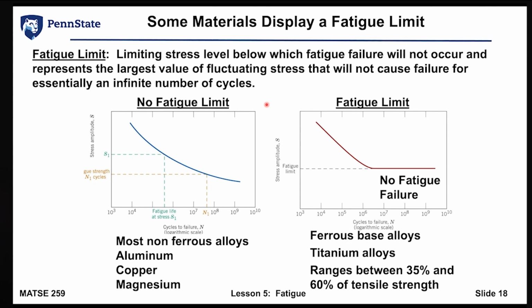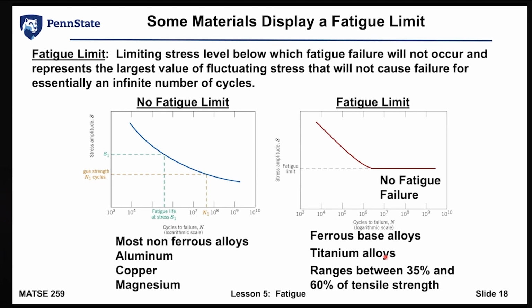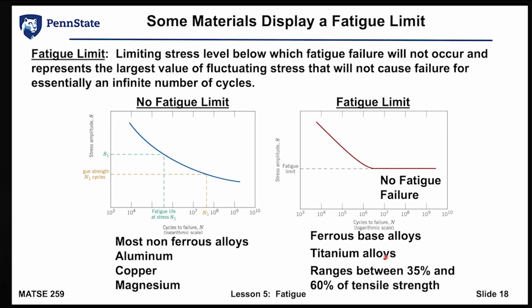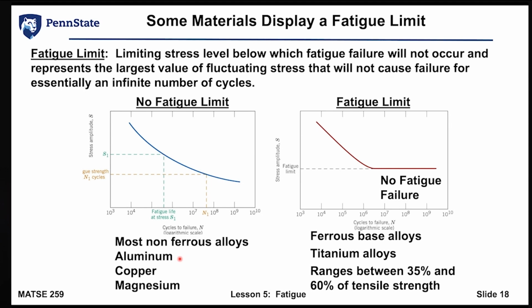If a material displays a fatigue limit, or an endurance limit as another way to put it, and typically ferrous-based materials and titanium alloys do, it is typically between about 35 and 60% of the tensile strength. We just make parts big enough that we get the stress levels down below this fatigue limit, so we can make ourselves feel a little better that we don't have to worry about fatigue. So fatigue becomes not an issue. Now, what we notice here is that non-ferrous alloys tend to display no fatigue limit, things like aluminum. Where do we use aluminum a lot? Aircraft. So when we think about how aircraft are going to operate, aircraft are susceptible to fatigue failures because of the material choices we made.